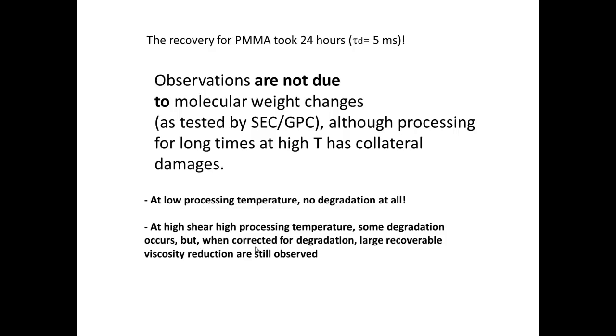As I said here, the recovery for PMMA took 24 hours. Tau d is 5 milliseconds. Observations are not due to molecular weight changes, as tested through SEC GPC, although processing for long times at high temperature, and especially when there is no nitrogen flowing, has collateral damages.